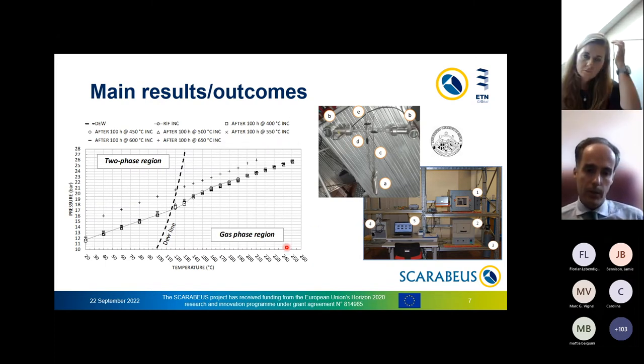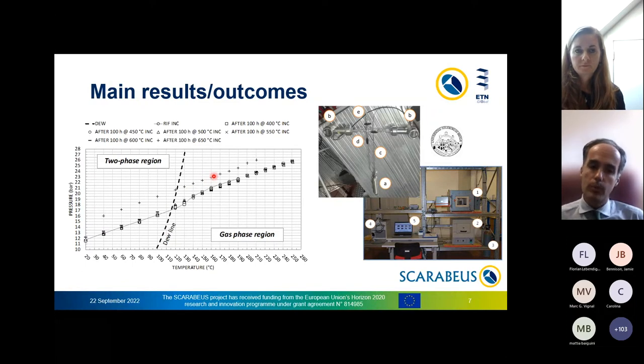This is a thermal stability test that you can see here, and this is the apparatus that you need to perform that experiment at the University of Brescia. So you can see here, pretty much all experimental values stick to the expected behavior unless you go up to about 650 degrees C, in which case you depart from the expected line, meaning that you are degrading the